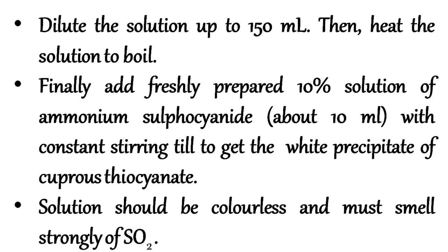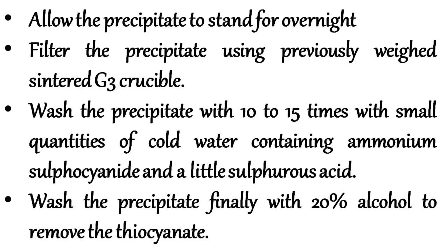The white precipitate of cuprous thiocyanate forms. The solution should be colourless and must smell strongly of sulfur dioxide if the precipitation has been done correctly. Allow the precipitate to stand for several hours, preferably overnight.